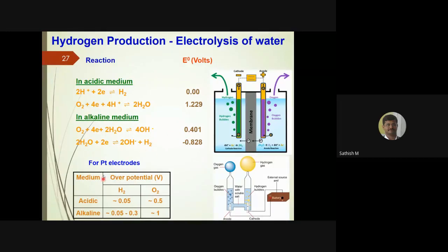These are the overpotentials I put in for your understanding. In the case of acidic medium, the hydrogen overpotential is very low, whereas the oxygen overpotential is very high. Almost 0.5, or 0.55 volt, is excess that you have to give for the process. Whereas in the alkaline medium, you could see up to 1 volt you should give for water electrolysis.